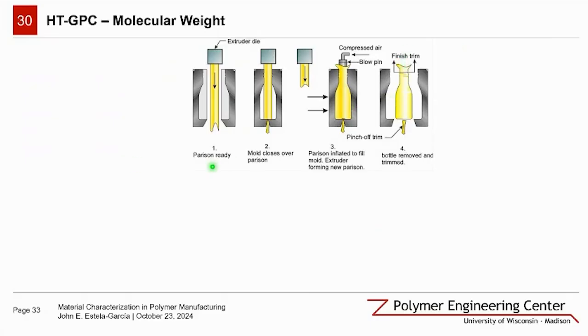In blow molding, the polymer behavior during the parison formation, which is this particular step here, is critical. The parison is a hollow tube that forms the starting point of the process. A well-formed parison ensures even wall thickness, proper material distribution, and minimal defects. Molecular weight analysis helps predict the behavior and optimize processing.